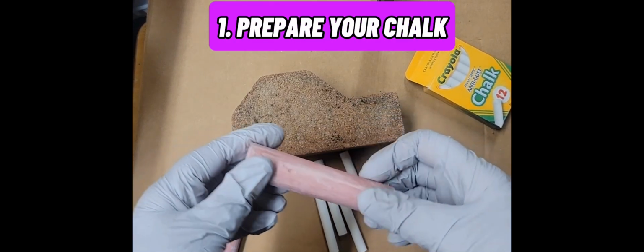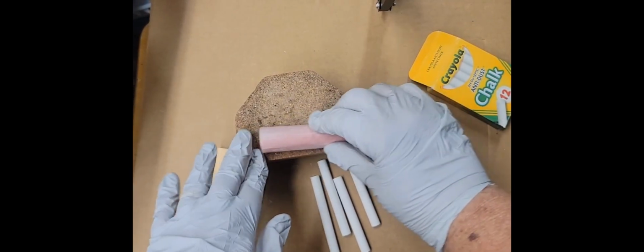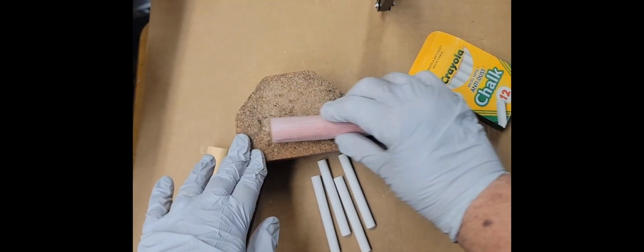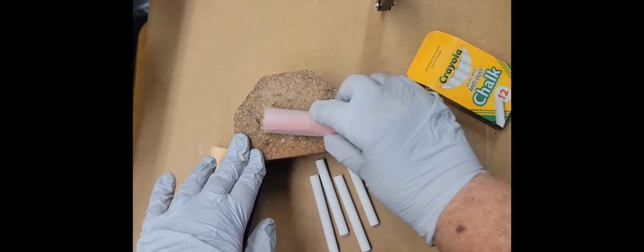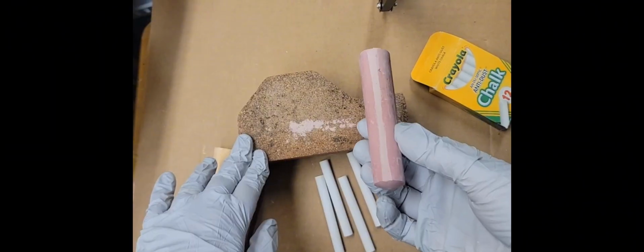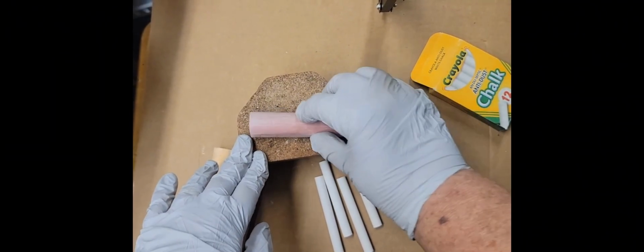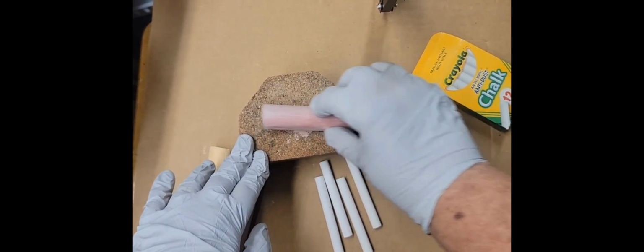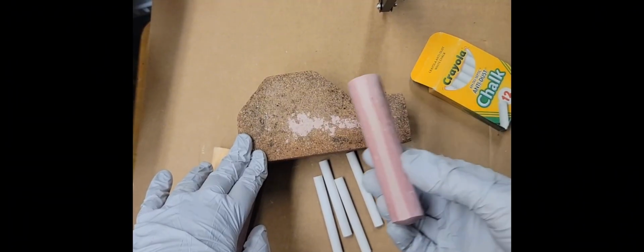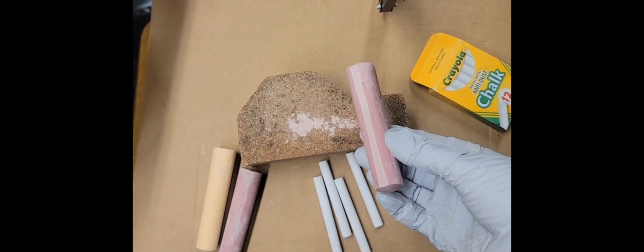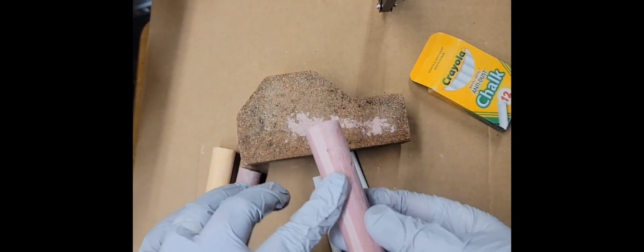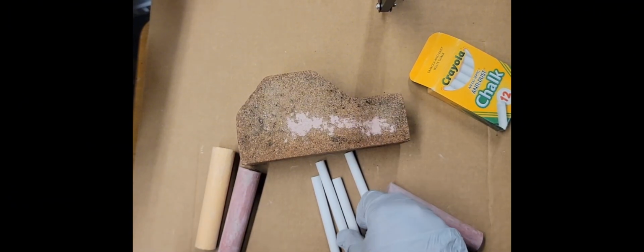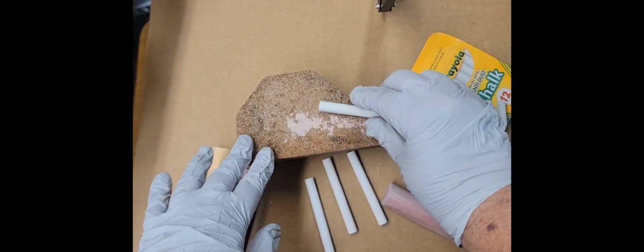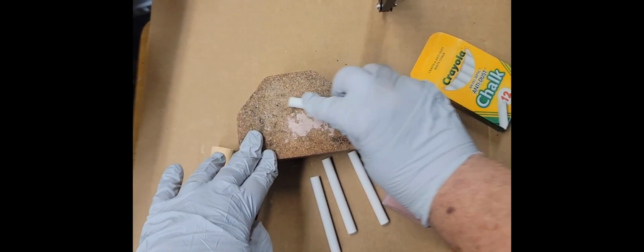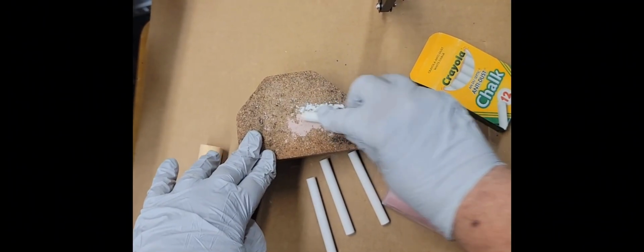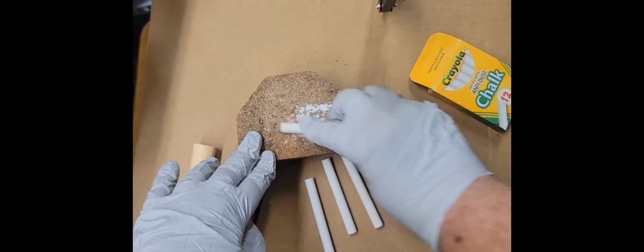Prepare your chalk by rubbing it flat on any rough surface so it won't roll around in your kiln. You can use an emery board, coarse sandpaper, or any convenient sharp corner or rough surface. If the dust flies, be sure to wear a mask. I like to use this brick because it traps the chalk dust, it's washable, and I can reuse it. You can refire your chalk, but it will eventually disintegrate after a few firings. Colored chalk is okay, but do avoid new types that might contain extra additives.